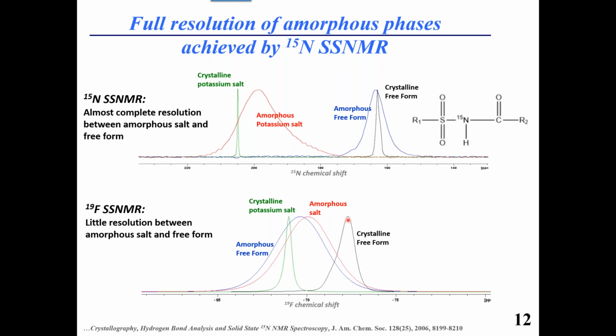Right. So the short answer is yes, but you have to catch them. We have freedom to change temperature, so you can freeze the rotamers. If they are dynamic, you will see the average. If you can distinguish two rotamers at a given temperature because they are quasi-static, then you will see two sets of peaks basically, and you can distinguish.